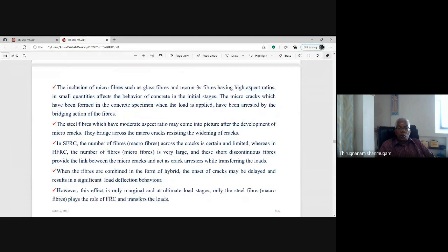These are the conclusions. In SFRC, the number of fibers, macrofibers across the cracks is certain and limited, whereas in HFRC, the number of fibers, microfibers is very large, and these discontinuous fibers provide the link between the microcracks and act as crack arrestor while transferring the loads. That is why the improvement in properties is noted.